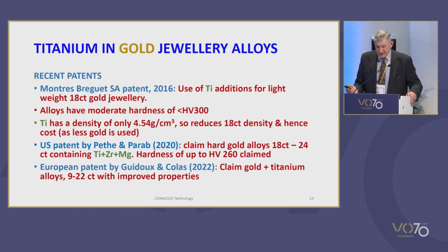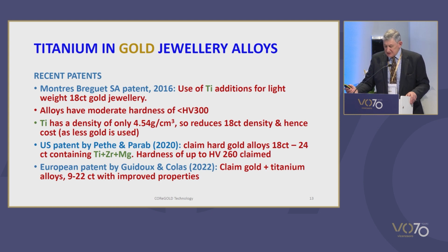There are some recent patents that involve the alloying of titanium into gold alloys. In the European patent in 2016, Montres Breguet SA claim a lightweight precious 18-karat gold alloy containing at least 75% gold, containing titanium and other elements in certain proportions, some of which act as a grain refiner. The alloys of this invention have a moderate hardness of less than 300 Vickers, it is claimed.